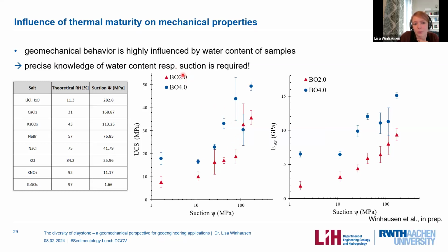You can see again here for the BO2 and the BO4 that I just showed you. And it's a really good result that we actually have 2 times higher UCS values for the location that has been buried, I think it was, 1,000 meters deeper. This is a really, really good correlation. So not only the UCS, but also the elastic properties: the higher the burial depth was, the stiffer the material is.